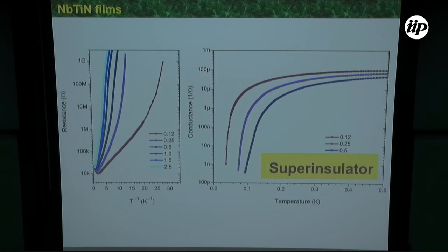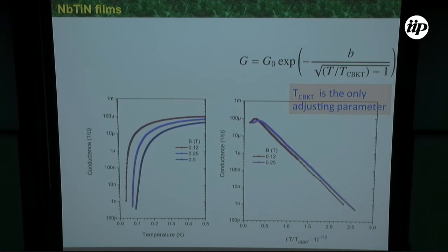What we have called super-insulator, but as I have said, is it super-insulator for us? Only, only, if it is shown that it is really charge BKT transition. Let's try to play with this very simple formula. This is the same formula which you have seen before on the superconducting side. We have only one adjusting parameter. And you see, again, the conductance follows the above equation about five decades. Great. Really, already at this point, I can say, guys, what you see now, you see first in your life. And so it is, that's it. But I will go further.